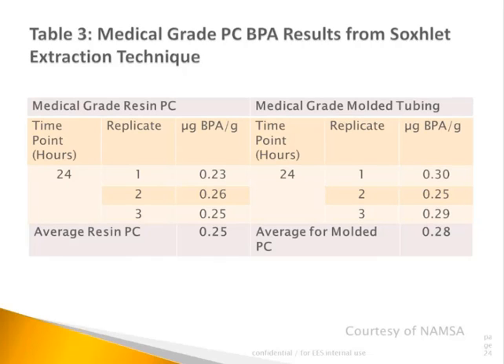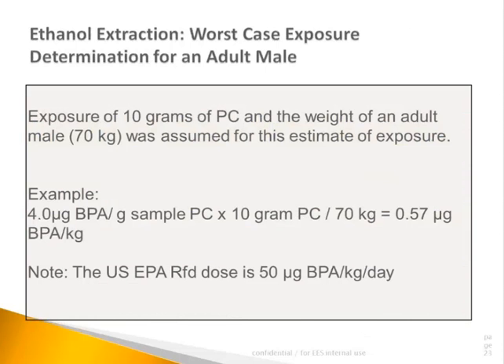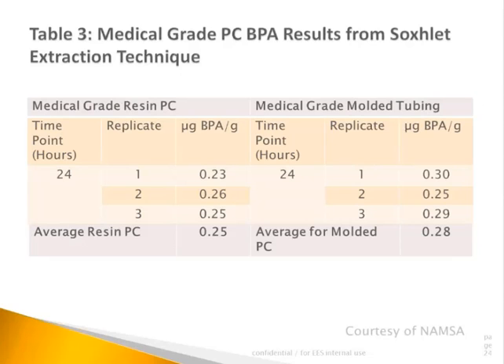Unlike the IPA extraction and the ethanol, the exhaustive extraction by Soxhlet was conducted just on the medical grade polycarbonate. The intent was to improve the level of detection by utilizing the most aggressive technique via analytical method combined with IPA. Medical grade was selected due to its linkage to our business model. And with that, the average BPA found to contain in the resin prior to injection molding was 0.25 microgram per gram polycarbonate and 0.28 microgram per gram after the injection molding.